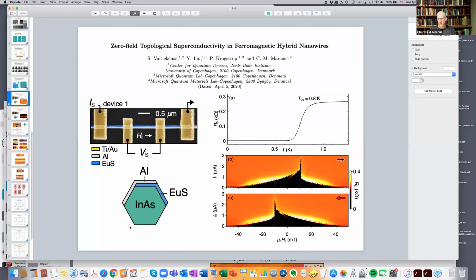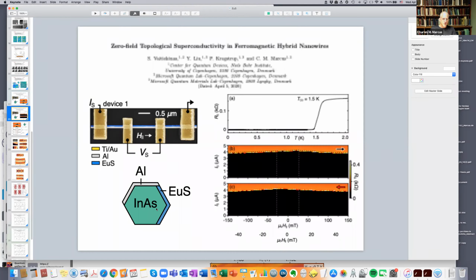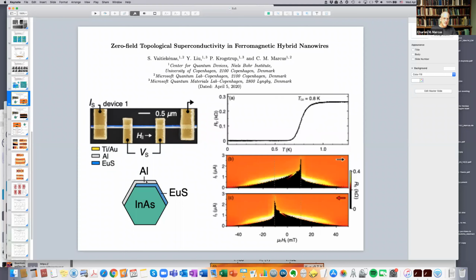If you don't mind, I'll say it a slightly longer way. The field that's inside the indium arsenide is the result of a proximity effect from a spin split superconductor. The superconductor has an exchange field in it, and I believe that this is true, and it's these data that make me think it, that there's nothing very much going in directly from the europium sulfide. I think what's happening is that the europium sulfide is going into the aluminum here. It's spin splitting the bands in the aluminum, nearly destroying superconductivity in the aluminum. But what we have is a Tedrow-Meservey spin split aluminum here, and that spin split aluminum is then proximitizing the spin orbit nanowire. That's what I think is going on.